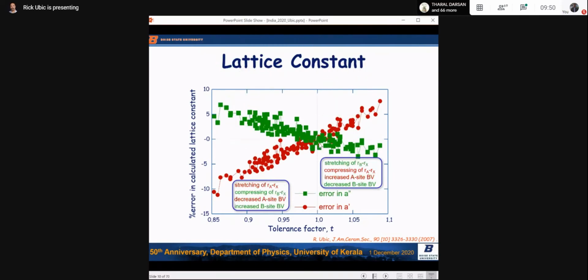If we use A double prime to do the same thing, we get this. We get the green data points. It's almost a mirror image, not quite. And we get the opposite effects. Using A double prime over here means we have a compression of BX bonds and an increased B site bond valence, and the opposite over here, stretching of BX bonds and a decreased B site bond valence.